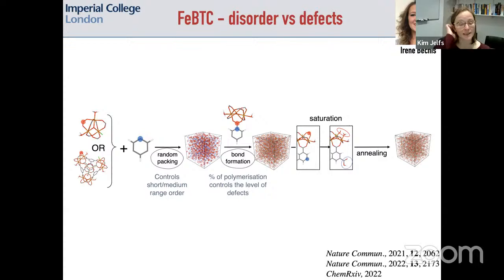So in Irena's case, what was interesting about what she could do with the potential FeBTC structures is that we, at the modeling level, have a control of the degree of disorder and also the degree of defects. If I explain how we do that, in terms of the degree of order, we can put in different sized building units. As you've got on the left, we can just put in the relatively small unit, or we can build up to larger secondary building units like the tetrahedron. So that controls the degree of short, medium range order based on how many of those we throw in at the initial stage. And then we can control the level of polymerization, so how many bonds are formed, and therefore how many remaining defects you get, where the defects are unreacted end groups.